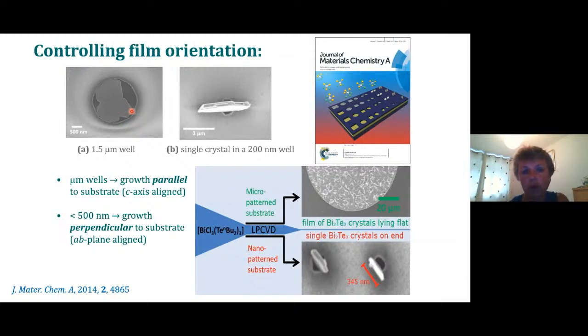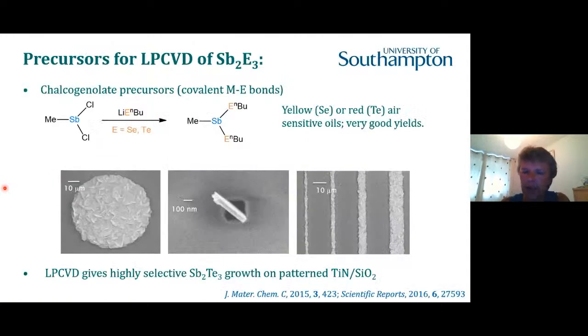If we take the lithographically defined recess diameter down, so this is now down to 200 nanometers, what we do is turn these crystallites up on end, and now we have the C-axis perpendicular to the substrate. So we get a remarkable degree of control of the orientation of the crystallites as we define the substrate underneath. And that's illustrated in this graphic at the bottom here. So that's a very nice situation for bismuth telluride.